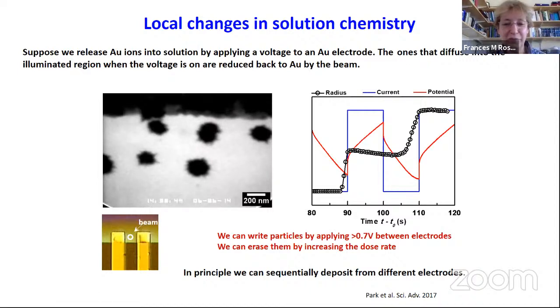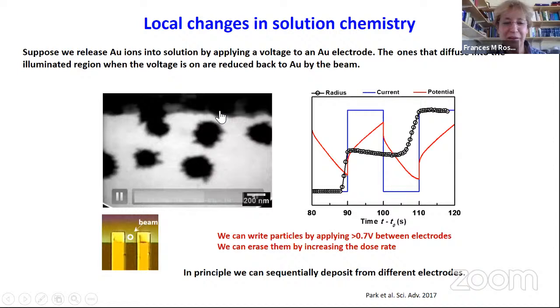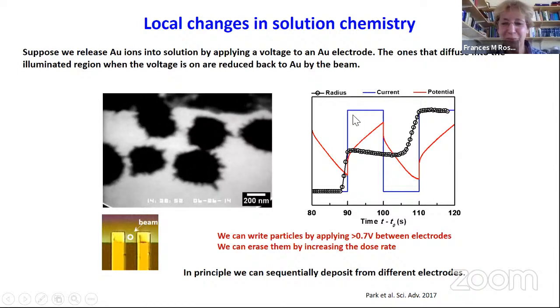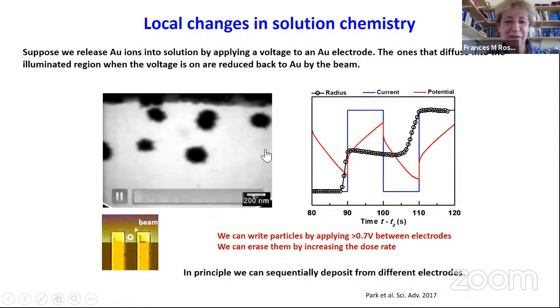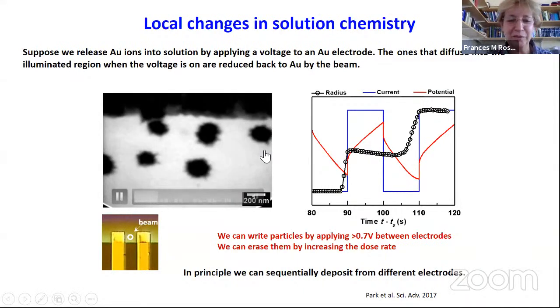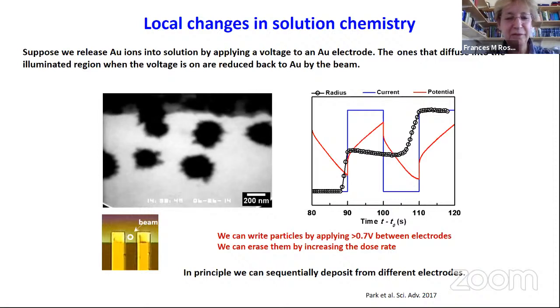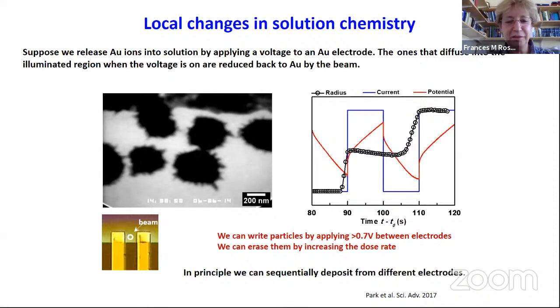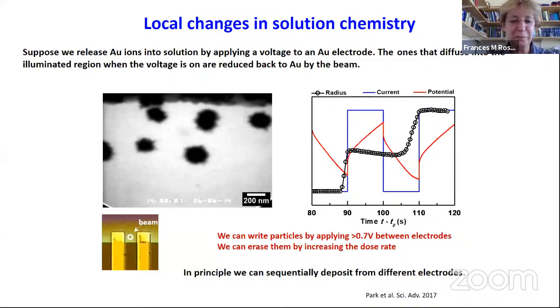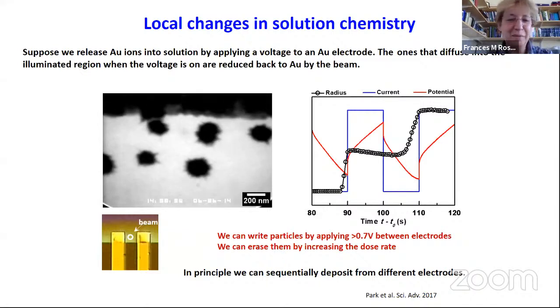And we can turn on the voltage. We're actually turning on the source of the ions by switching the potential off and on, the current off and on. And you can see that they only grow when the voltage is on. So it's kind of an interesting illustration of the process of releasing the ions into solution at a certain time, and then they diffuse along, and then the electron beam reduces them back into particles. So you can, in principle, maybe track the diffusion of the ions off the electrode.